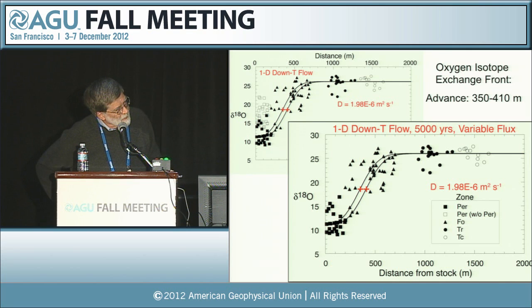Okay, there's some variations you can play with the fluid flux here. So again, here are the two estimates of the positions of the center point at 350 and 410 meters. And these are the profiles constructed at 2 times 10 to the minus 6 for the diffusion dispersion coefficient. What I've done is emphasize the solid symbols, which are close to the intrusion, the periclase-bearing samples within the nominal periclase zone, and they represent the overwhelming focus and flux of fluid flow here. So I've just given them more importance. Again, we could play around a little bit here with fluid flux.